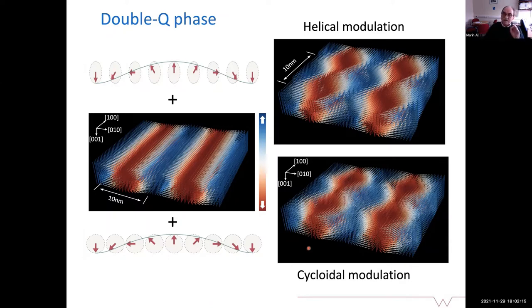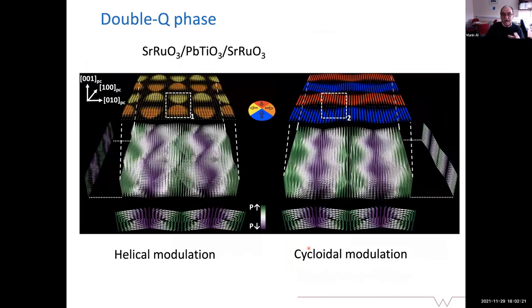Exactly similar as the IC2 phase in the strontium ruthenate. Now, we have analyzed the polarization pattern from the top and from the side. We did transmission electron microscopy along and perpendicular to the vortices, the vortex core. And we're almost convinced that this is a cycloidal modulation of this vortex core.